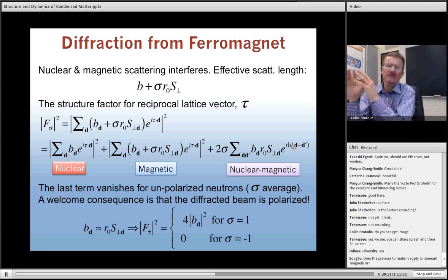So we have to look elsewhere to make the distinction between an itinerant magnetism and a localized magnetism. In the diffraction cross-section, it's pretty difficult to pick up. So typically we might need to look at the nature of the excitations, or we may need to look at the pressure dependence of the magnetism, other more intricate experiments to really make a determination as to what is the appropriate way of thinking about that type of magnetism.